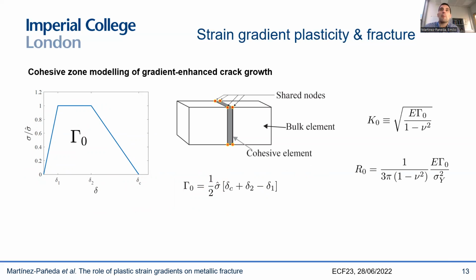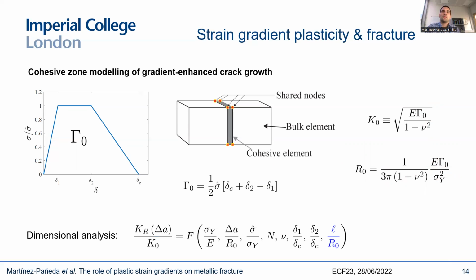And then, as in their paper, we can define a critical or reference stress intensity factor at which cracking will initiate, whenever that corresponds to this fracture energy. And then you can also define a characteristic length of the fracture region, this R0, characteristic length of the fracture process zone, that depends on the fracture energy, the yield stress, Young's modulus, and so on. And if you do a dimensional analysis, what you see is that the R curves, the crack growth resistance curves that you will predict, are essentially a function of these non-dimensional sets.